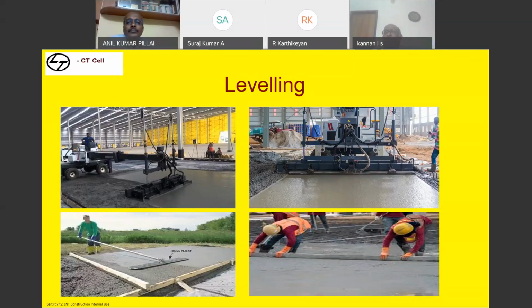And normally the level difference we are observing may be over meters of length. See, the difference may be 3 millimeter. So that can happen. In other project sites, you can even use a bull float, because normally in Indian conditions, we are not using bull float at all. Bull float can be used for making the concrete finish, so that the finish can happen in an excellent way and leveling can happen. Straight edge also can be used for leveling. It's not that you should not use it. So depending upon the volume, we can decide what type of equipment is needed. Only for larger scale or industrial flooring, laser screed is the best, where we can do the job with more stringent quality norms.